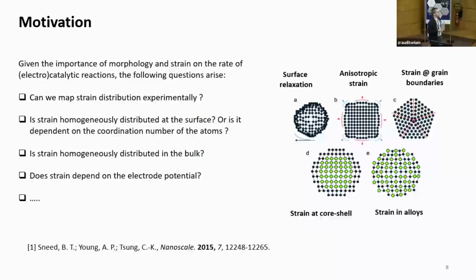When we started this work like 2 years ago, it was like a dream to be able to map the strain distribution, because the morphology, but also the strain on particles have a strong influence on the rate of electrocatalytic reaction. So first, we wanted to know whether we could map the strain distribution.